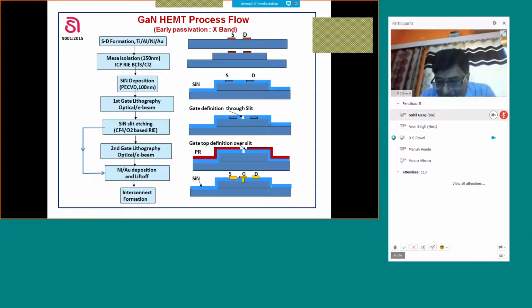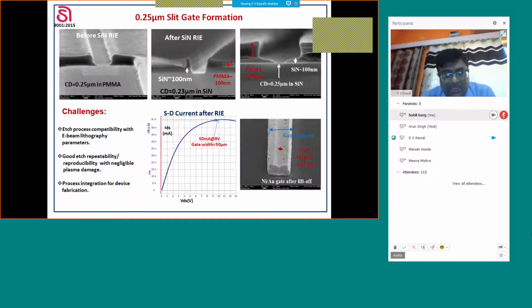So my footprint is reducing the gate length, and this is important for high cutoff frequency, but I need low gate resistance also. So this broad head is increasing the cross section of the gate, and reducing the overall gate resistance. This technique is normally used, and you can see that this is EBL, electron beam lithography, defined 0.25 micron gate dimension, and then this is showing the silicon nitride layer etched by dry etching in a controlled dimension. Again, this is 0.23 micron, and then this metal deposition is carried out, and this is how the T gate looks, because this dip in the center is basically the slit, which is the gate footprint.